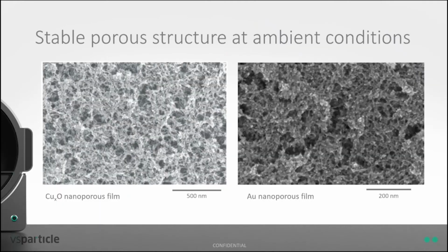So two examples of these nanoporous layers. On the left you see the copper oxide nanoparticles, and on the right you see gold. And in both cases you get nice porosity. And this porosity is also a key feature that we are currently using in scaling up the production of SERS sensors for molecular diagnostics.